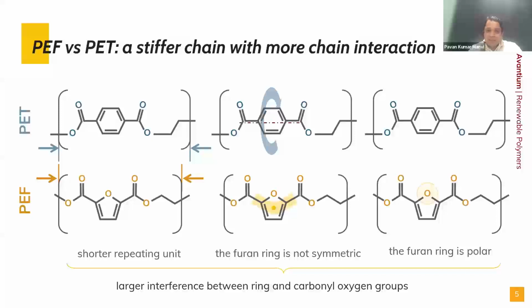If we compare these two rings, in the case of PET, the benzene ring, or the 6 carbon atom ring, is symmetric and it can flip around, which gives nanoscale rotations and also the possibility of flexibility. But in the case of PEF, this furan ring is not as symmetric as the benzene ring, and therefore the rotational frequency is very much restricted. And due to the oxygen atom in the furan ring, it is also more polar than PET. So these are the differences.